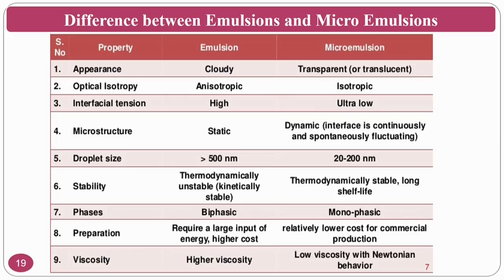Normally the first and foremost thing that you see is droplet size. Droplet size in an emulsion will normally be greater than 500 nanometers. But in some of the other papers, they give this range as 1 to 10 micrometers and all those things. In some other papers, micro emulsions are in the range of 20 to 200 nanometers or slightly above, plus or minus 10 or plus or minus 20. The second thing you can see is interfacial tension: in emulsion it is high, here it is ultra low. So low interfacial tension means it is easily miscible and all those things. Remaining, viscosity: emulsions are highly viscous and these are low viscous. If you see low viscous, what will happen?